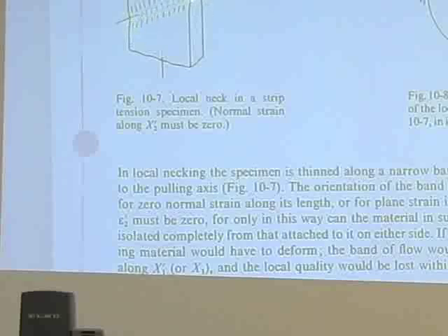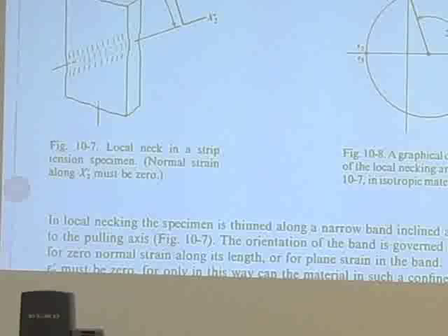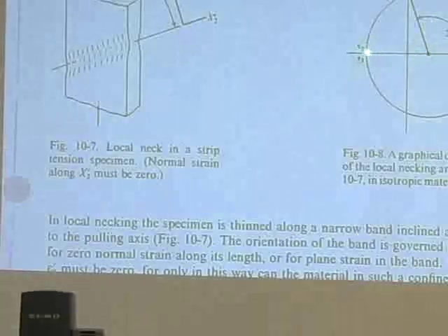First of all, if you form a localized neck, it must be a state of plane stress, or plane strain, okay? Because there's no strain in the x2 direction. It's not changing length because the material on either side is not deforming at the same rate. So you can do a Mohr circle diagram, an elasticity Mohr circle diagram where e2 and e3 are Poisson's ratio times e1, and Poisson's ratio in elasticity might be 0.3, 0.33, something like that. So this is not a plastic Mohr circle where the Poisson's ratio is 1/2. It's an elastic Mohr circle where the Poisson's ratio is like 0.3, and you draw to where you have a plane strain condition.